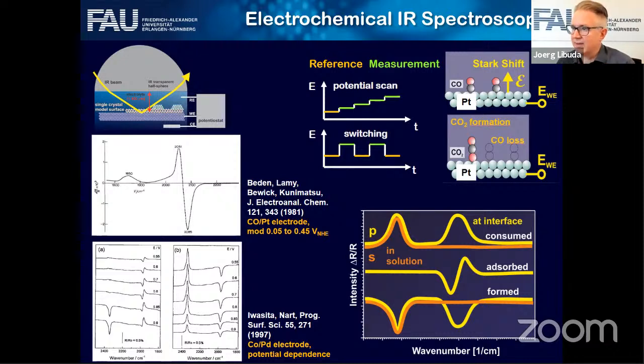There's an implication to that. The implication is that already at the time when you're taking the difference, there may be adsorbates on the surface. If this is the case, then of course if you lose these adsorbates, you will have a peak in one direction in the difference. If you accumulate adsorbates, you will have a peak in the other direction. So you can have positive and negative peaks. If you're unlucky, maybe the adsorbates are there all the time, and then it gets difficult.